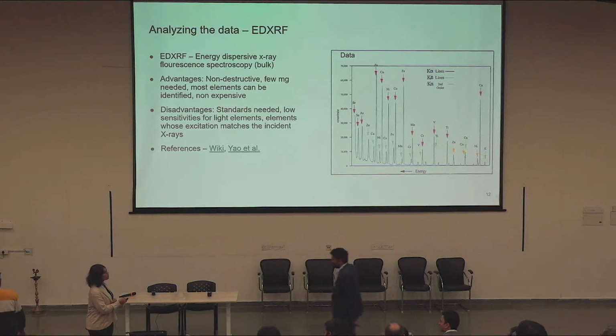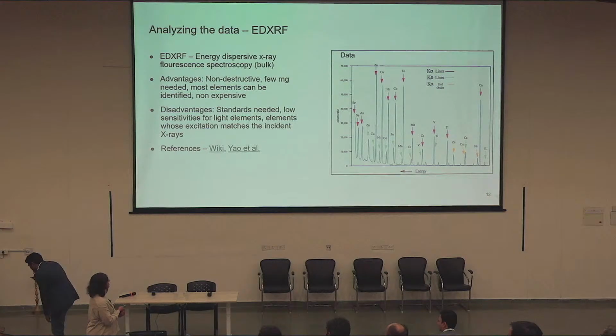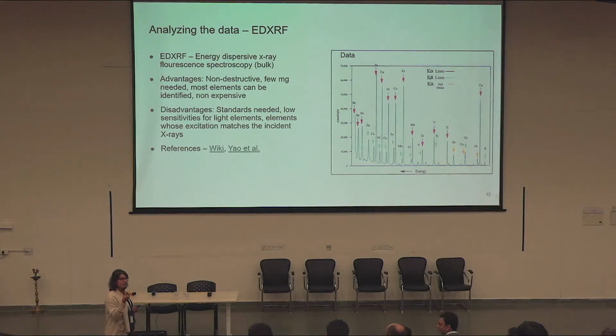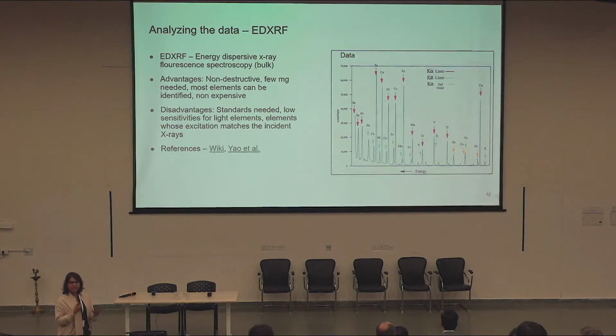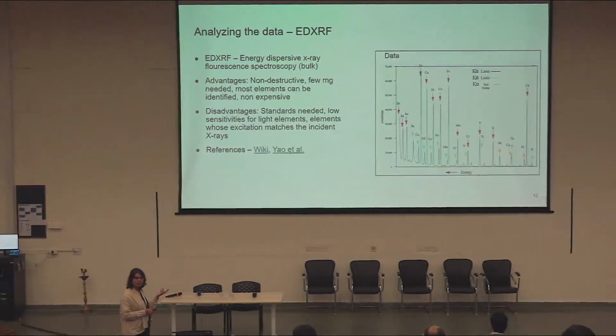So this is the kind of data that you get from the EDXRF. Okay. Basically, what you get is intensity or the counts on the y-axis, and the x-axis is nothing but the energy of the emitted X-rays. So what is happening is that when I have multiple different elements in my sample, depending on the identity of the incident X-ray, I am going to excite different kinds of electrons in my element. And that is going to result in different kinds of fluorescent X-rays that are emitted out of my sample. So these are the kind of peaks that you would get for typically the metals that are present in your sample.